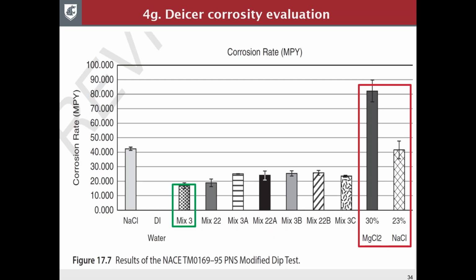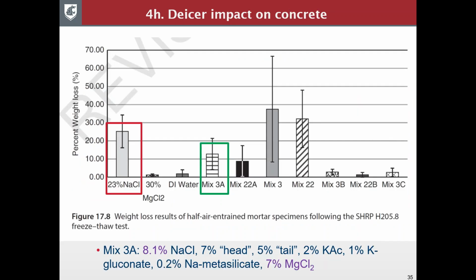And we also tested the corrosion to carbon steel. Following the Pacific Northwest Snow Fighters Association test protocol, mix 3 was much less corrosive to carbon steel than the salt brine. Actually, many other products had the same feature. Now, in terms of impact on concrete, we followed a SHRP freeze-thaw test in the presence of diluted liquid deicer. Everything is diluted 3 to 100 by volume. In this case, you can see mix 3A, which was blended with some magnesium chloride instead of 23% sodium chloride, and the scaling loss was much less.